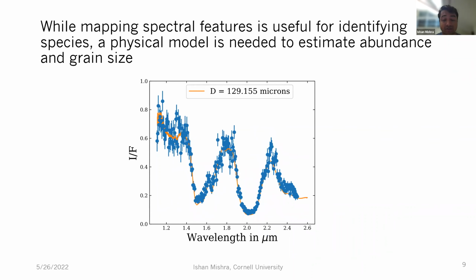And once you have identified species, once you have your candidates for what you're seeing, the next thing we want to do is get at the abundances. So how much of what is present, and for that we rely on modeling the reflectance spectra. So we're fitting the data with a model, and the model is not just incorporating the effect of the different amounts of different species present, but also physical parameters like grain size of the regolith, porosity of the regolith. Because as shown in this GIF, grain size is an interesting parameter where it changes the absorption feature strength and also shapes, and hence becomes degenerate with the abundance. And so it needs to be taken into account when you are doing the fits, so that you have correct estimates or conservative estimates on your abundance.